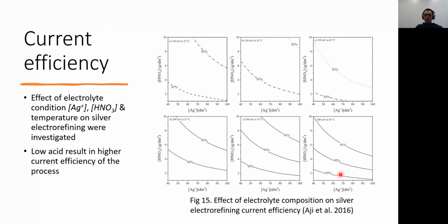This is, if I'm not mistaken, the first or the second paper that I published. I studied the effect of the electrolyte condition, the silver content in the electrolyte, nitric acid, and temperature on silver electrorefining. As we can see here, I put different overpotentials in this process from 150 to 200 millivolts, different temperatures, and concentrations of acid and also of silver. And it produces quite interesting current efficiency.